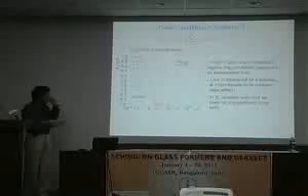So now this quantity depends on the wave vector. I don't want to go into detail, but what people care about is how the stretching depends on the wave vector, how the relaxation time, so the area under the curve, depends on the wave vector, and how the height of this plateau depends on the wave vector. For the self function, for example, the height here is basically a Gaussian function in Q. So it's e to the minus q squared, to a first approximation. So this is quite a good approximation.